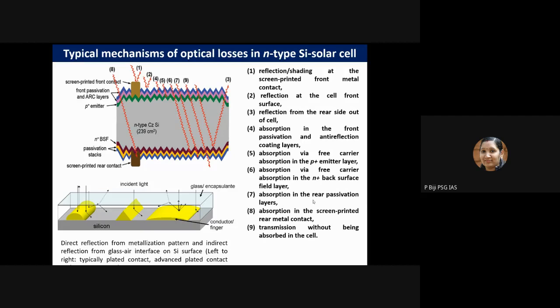Then absorption via free carrier absorption in the N-type back surface field layer. The seventh contribution will be the absorption in the rear passivation layers, absorption in the screen printed rear metal contact, and transmission without being absorbed from the cell. So that's the parasitic absorption, parasitic reflection. So different mechanisms exist as we discussed right now. So different contributions from different parts of the device are observed.